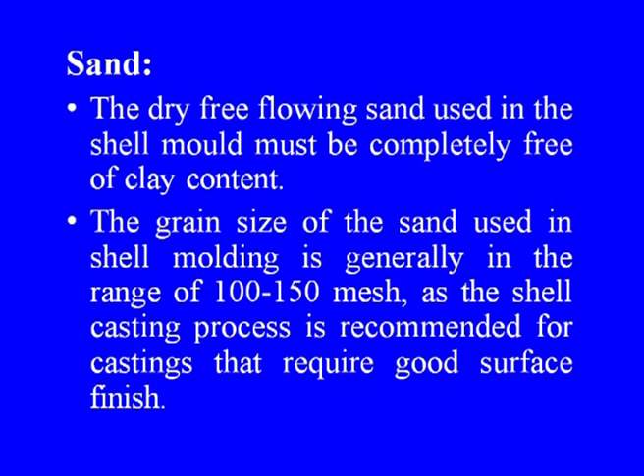The dry free-flowing sand used in shell molding must be completely free of clay content. The grain size is generally in the range of 100 to 150 mesh size, as the shell casting process is recommended for castings requiring good surface finish. However, depending on the surface finish requirement of the final casting, the grain size can be adjusted. If the grain size is very fine, it requires a large amount of resin, making it further expensive.